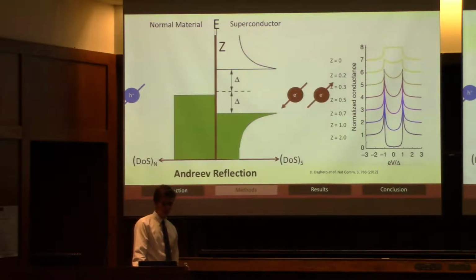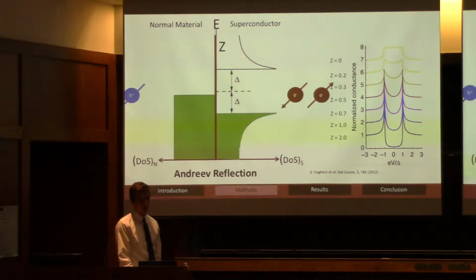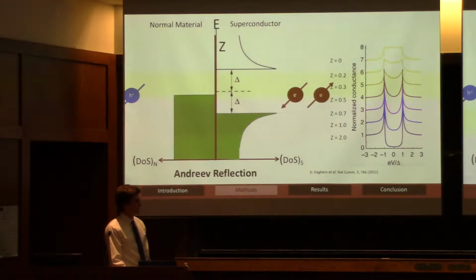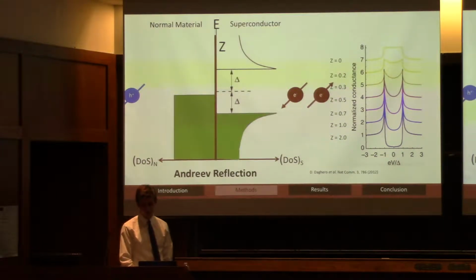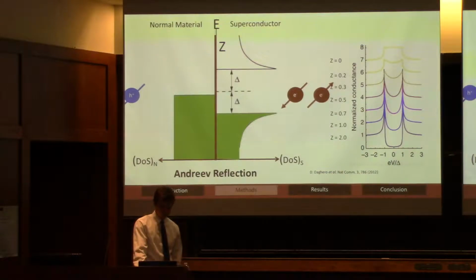And when you map that out on conductance versus voltage, which is what this graph is, this is your result. So those bottom darker lines are for a really opaque barrier, and you get a dip in conductance, and those top lighter colored lines, if you can see them, are for a very transparent barrier where you get almost perfect Andreev reflection, giving you a plateau in that gap. So this drives the measurements we do for our samples.